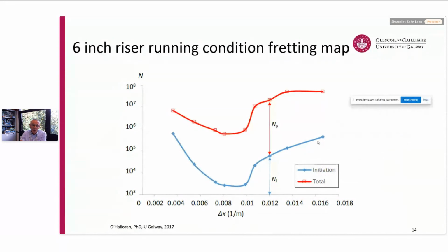And using our combined initiation and propagation fracture models, we can estimate the contributions of initiation and propagation, and we can identify critical regimes of loading, as you can see in this region, around about 0.008 to 0.01 is the critical curvature range, or cyclic curvature range, for minimum life. So we can then design against for maximum life, or we can design against critical situations, for example.